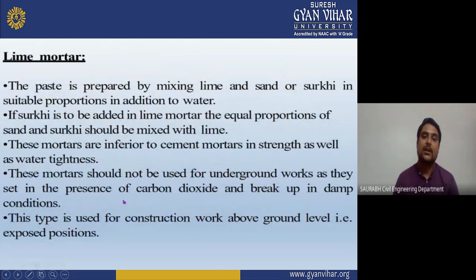Now we will see the lime mortar. The paste is prepared by mixing lime and sand or surkhi in suitable proportion with the addition of water. If surkhi is to be added in lime mortar, equal proportions of sand and surkhi should be mixed with lime. These mortars are inferior to cement mortar in strength as well as water tightness.